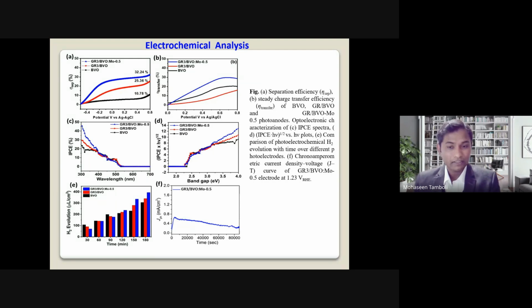in 3-hour light exposure. Furthermore, we have again checked the stability of the material by using chronoamperometry, and it's showing the 80% retention of photocurrent density even after 24 hours. This means that our material is very stable, very efficient, and it is useful for large scale hydrogen production.